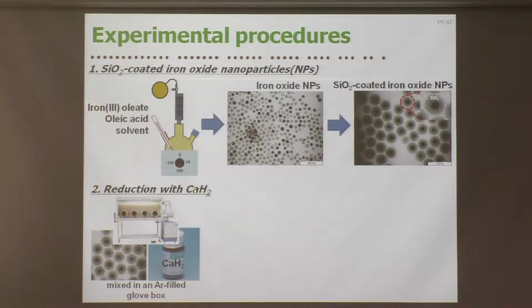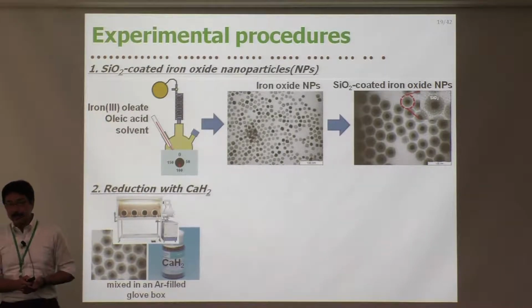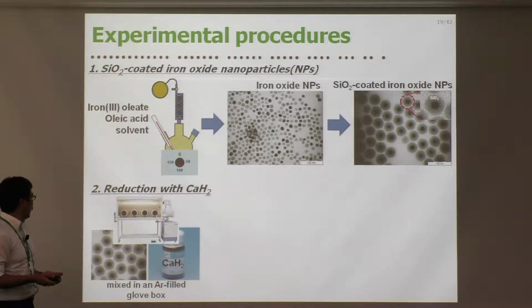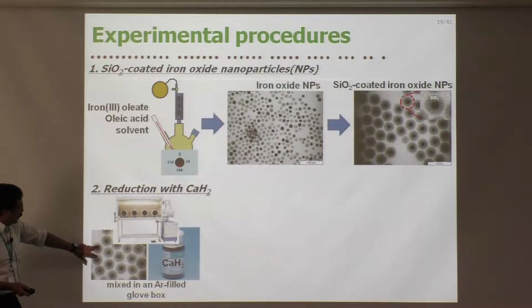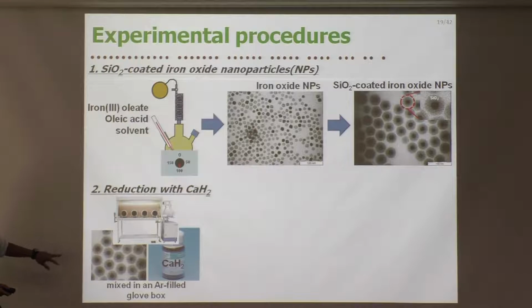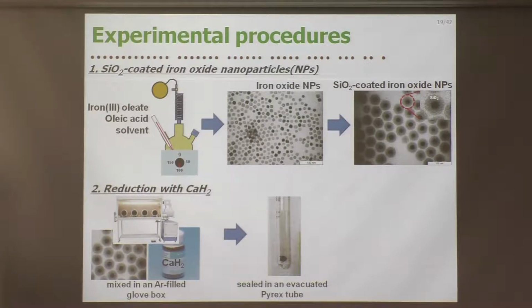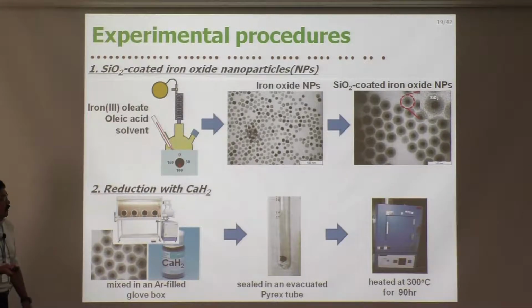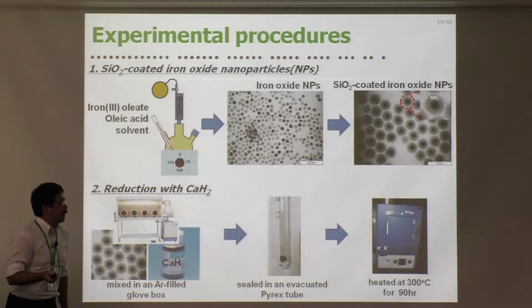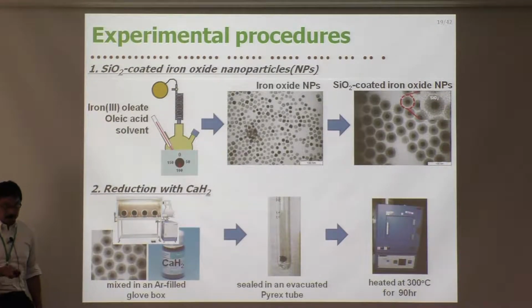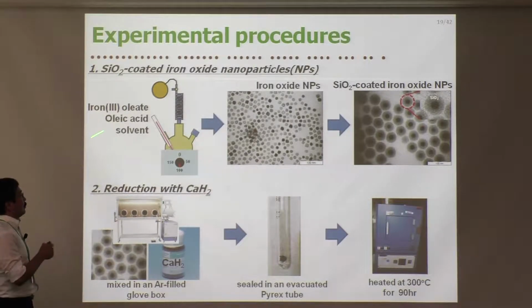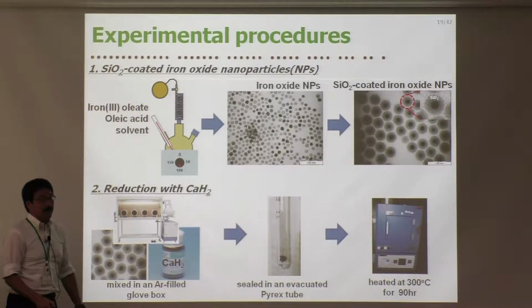The next step is reduction with calcium hydride. Because calcium hydride reacts with moisture in the air, we mix the calcium hydride and the SiO2-coated iron oxide nanoparticles in a glove box. Then we seal the mixture in an evacuated glass tube, and finally carry out the heat treatment. The typical conditions are 300 degrees Celsius for 90 hours. Through this way, we prepared the samples.